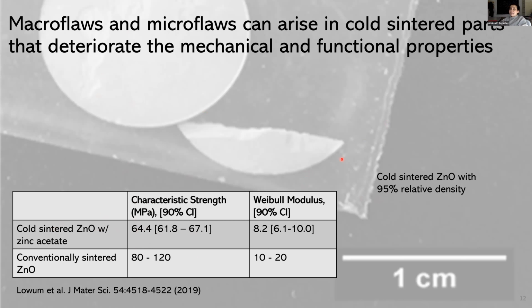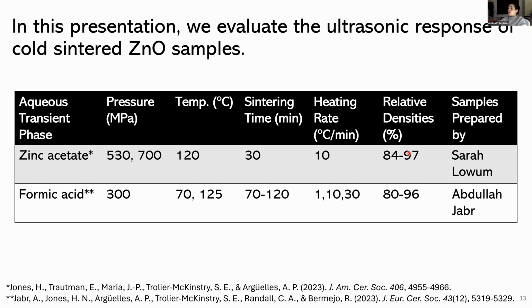Now, as I mentioned before, the standard is to use relative density measurements, and as you can see from the example in the back, and from some more in-depth data that we've collected, that's not necessarily reliable. So what we wanted to do was say, okay, if we create a set of samples that has some range of relative density, how does that compare in the context of their ultrasonic properties? And is that more representative of the mechanical and functional properties that we're getting for the parts?